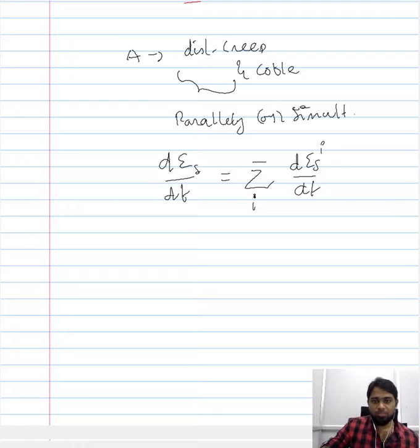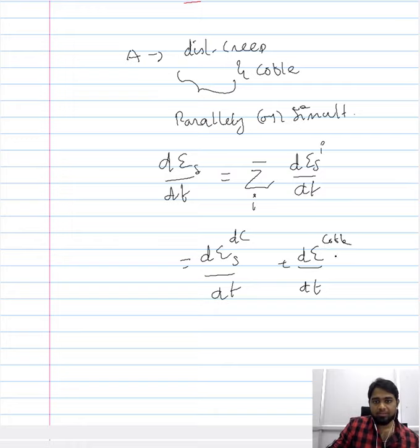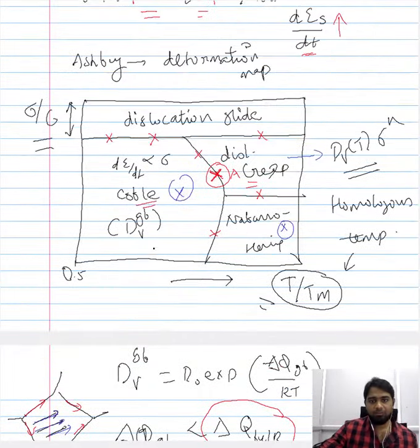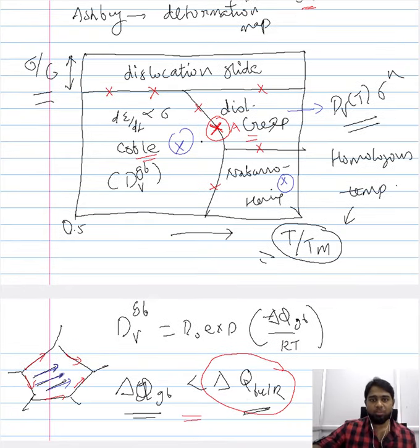So this would be the creep rate according to the dislocation creep mechanism plus the creep rate according to the Coble creep mechanism. When your point lies on the line, you have to take the summation of the two creep mechanisms that it separates. You have a definite expression for each creep mechanism, and when your point lies on the line that separates them, you just sum it up. The same goes for the points here. Let us mark it using blue.